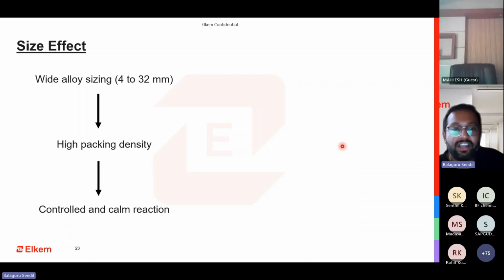And most interestingly, if you are using a wider size, you don't need to use so much cover. Your cover can be 50% of what your alloy addition is. If you're adding 1% of alloy, your cover can be only 0.5. You don't need to add a 1:1 ratio of cover, because getting the cover is always a challenge. The correct size, the chemistry, and also getting it uncontaminated is very difficult.